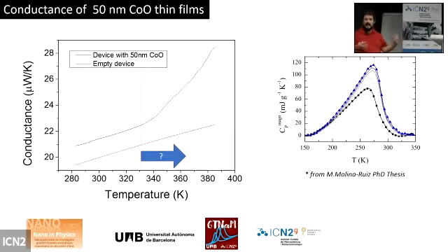We have a highly nanocrystalline material with a lot of grain boundaries, with a lot of oxygen that may be out-diffused, and this is related to the reduction of the cobalt oxide by itself.